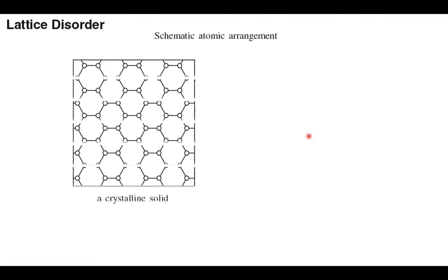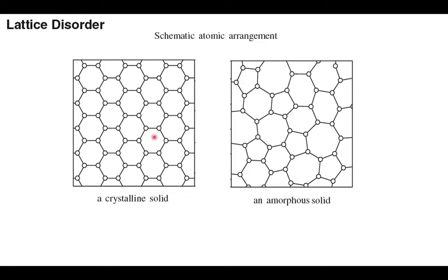Here is a schematic of the atomic structure, to see what kind of damage you get. If you have a crystalline solid, you have a periodic arrangement of the atoms. After ion bombardment, when you make this crystallinity amorphous, you have completely damaged the periodic arrangement of the atoms that you had in the crystalline state. You still have some sort of arrangement, but there is no periodicity in this distribution, so you lost the crystal structure, and this we call amorphous. All you need to do is anneal at some temperature, and then of course these atoms settle into similar structures again.